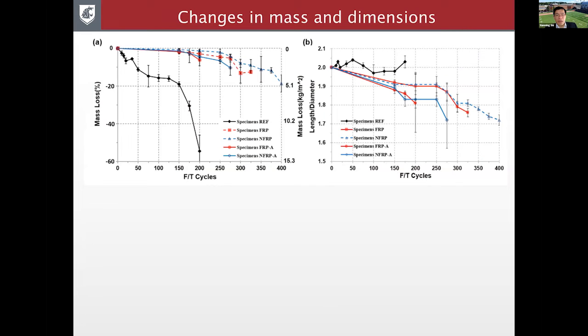So in terms of mass loss, you can see on the left-hand side, after 200 freeze-thaw cycles, the control group without FRP, you're seeing more than 55% mass loss. However, when you have FRP, whether it's nanomodified or not, you're seeing much less mass loss, so less than 20% after 400 cycles.